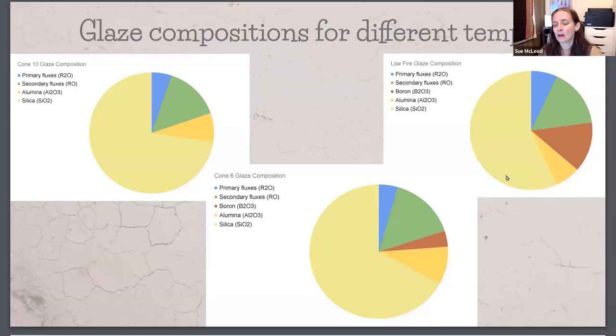And then at low fire, cone 04, for example, we have much more boron. So the fluxes are generally the same. They take up the same amount of space in the pie, but now our glass formers are divided up differently. There's way more boron, way more low melting temperature glass former, and less silica and alumina. That's so the glaze will melt at an even lower temperature. So it's all about proportions.